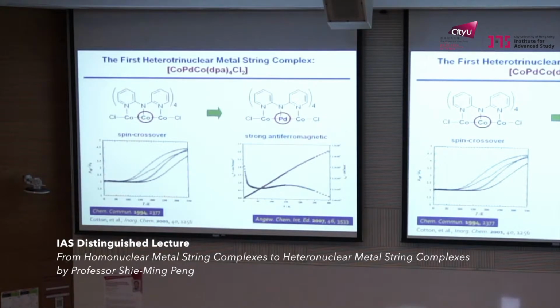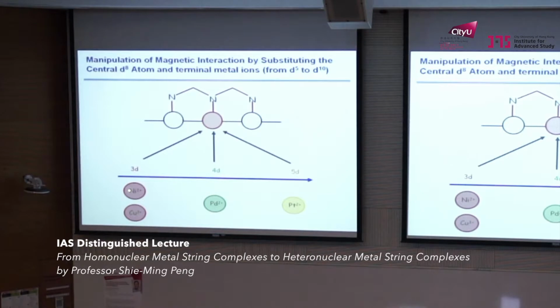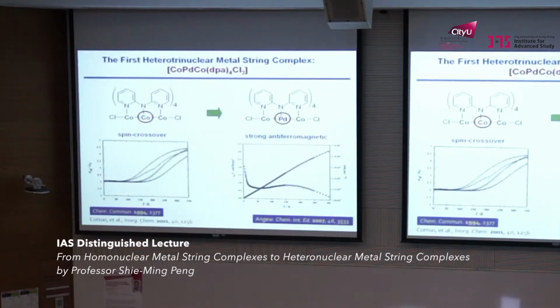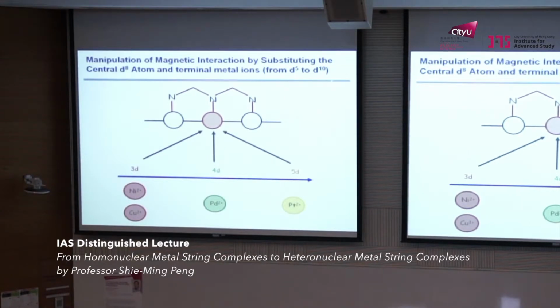Because these 3 nitrogens have different donating power. If you use the Pauling resonance concept, actually this amido carries half of the negative charge. Pyridyl only carries a quarter of negative charge. So they are different. And the central one prefers the D8 metal because of the square planar geometry, if you neglect the metal-metal bonding. So I call it thermodynamic control because the middle one prefers D8 metal. And this structure, cobalt, shows anti-ferromagnetic coupling. From this point, I can choose nickel 2, copper 3, palladium 2, platinum 2 as the central one. And the terminal, previously D7, now I can synthesize from D5 all the way to D10.